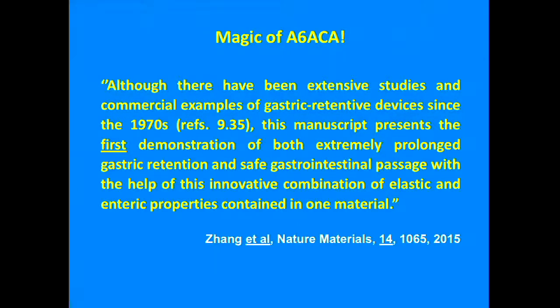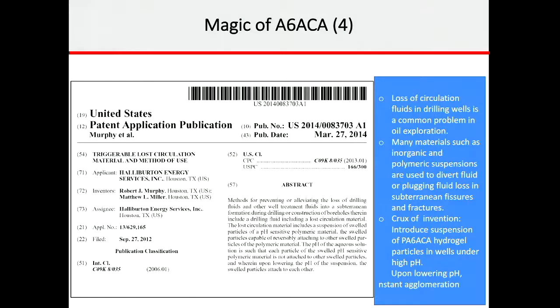But Elizabeth, when we were having that accident in our poor laboratory because of the rusted oven and so on, we never knew that the result of that will be finally creating something that is the best that is said after 90 years. Another amazing application, Mark, here, Halliburton has done it. This is about the oil well drilling issue, because there is a loss of circulation fluids in drilling wells. It's a very common problem. So they use a lot of materials, inorganic, polymeric, etc. So what they did was to introduce these PA6ACA hydrogel particles in order to do the block.